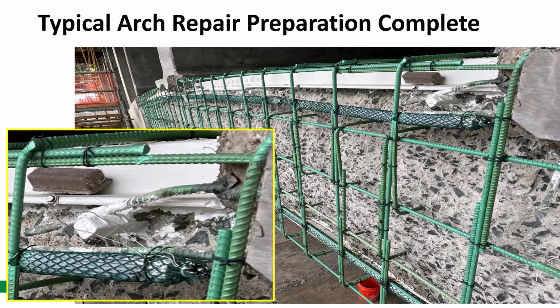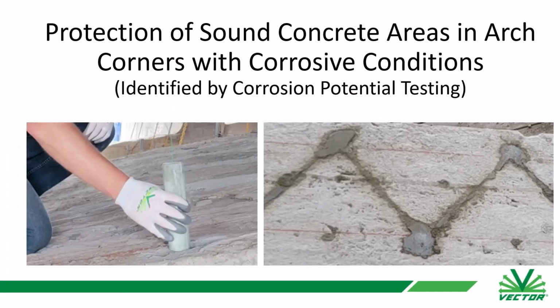And then at these interfaces where you have the new and old concrete, that protection was supplemented with the use of some of the XP or the smaller anodes. And you see here how the anodes were connected. They're not connected into the reinforcing steel like you typically see by turning the tie wires around. They're actually connected to a self-tapping screw that's been drilled into the structure. And so these are designed to give supplemental protection at that interface.